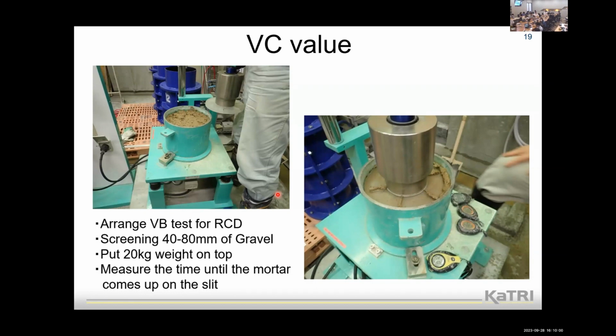The dam construction site often uses gravel. The maximum size is 80 millimeters or 150 millimeters. At our site, the maximum size is 80 millimeters. So we screen 40 to 80 millimeters of gravel and put the weight on the top.